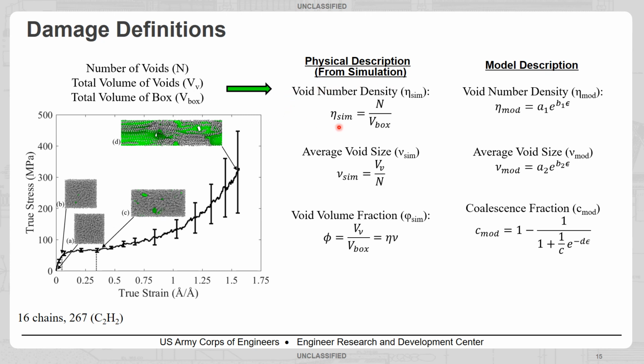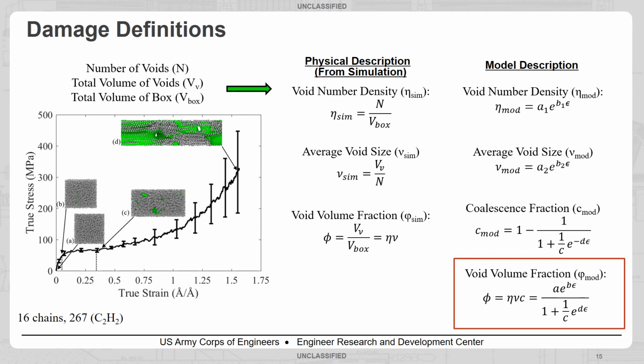This effect is inherently captured in the simulations just by the number of voids and the average size of voids, but it's not inherently captured in the models, so we need to define an explicit term for coalescence. So here we use this logistic growth equation. When you multiply nucleation times growth times coalescence, you get your total void volume fraction. Here, the equation looks like this: your exponential growth divided by this logistic growth. So it allows you to capture the damage response, as we'll see in a couple of slides. And that's the term that we're going to actually fit to our simulation results.